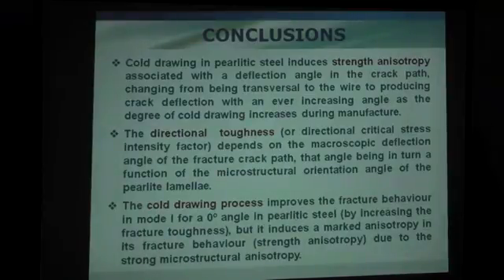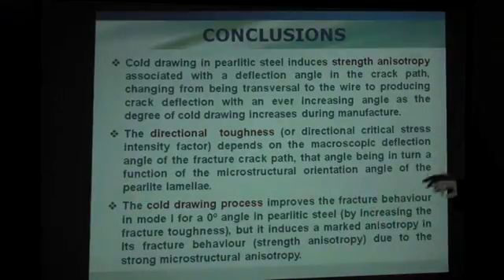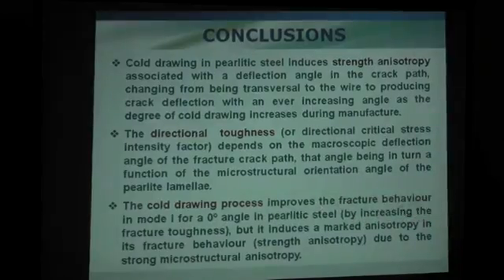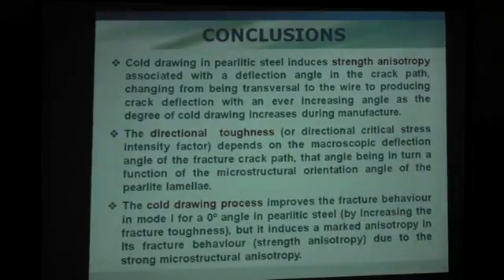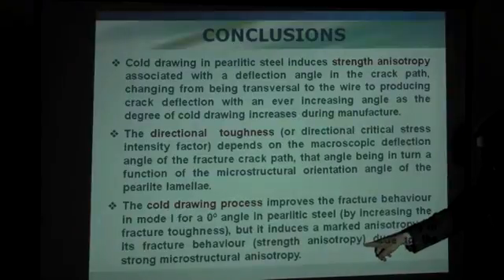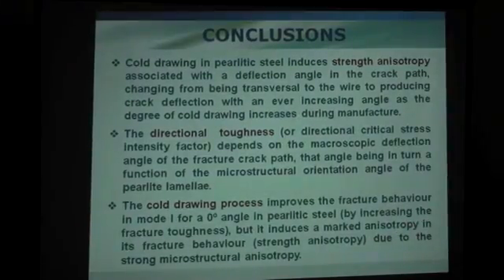This is the final point of manufacturing. But in addition, manufacturers don't know, they are not aware, but in addition, it improves the fracture behavior in mode 1 and the fracture toughness, the classical for transverse zero angle in pearlitic steel, by increasing the fracture toughness. But it induces a marked anisotropy in its fracture behavior, a strength anisotropy, due to the strong microstructural orientation. The strong microstructural anisotropy. And that's all. Thank you very much for your attention.